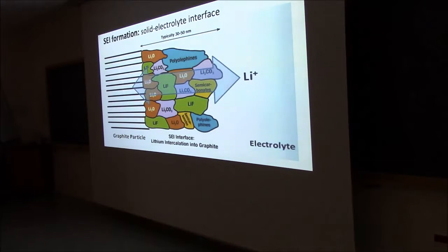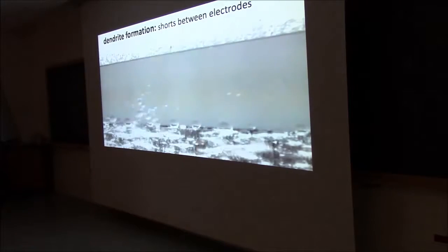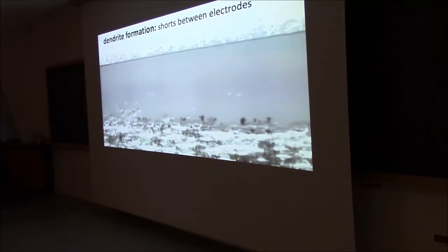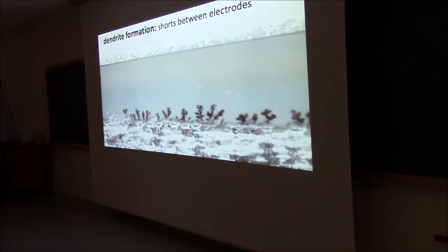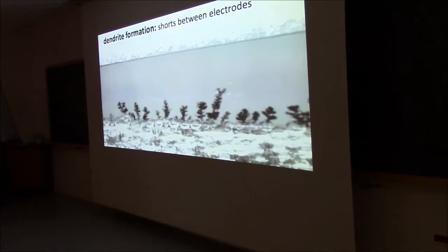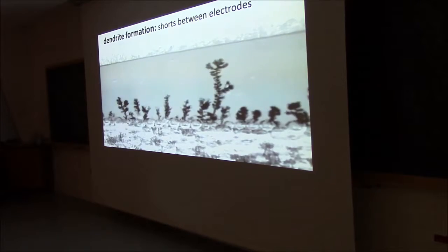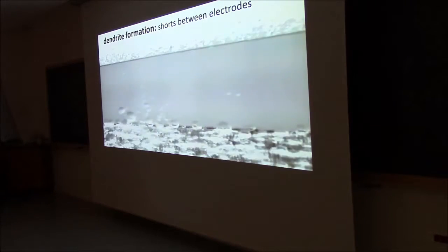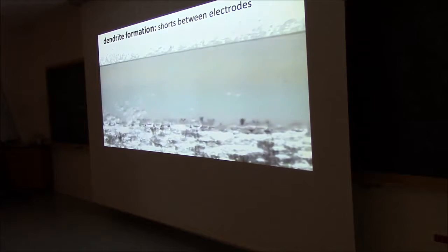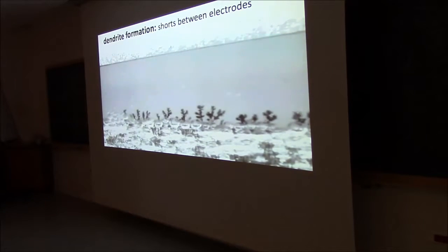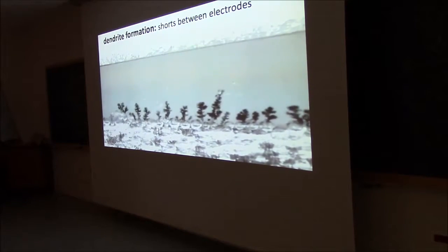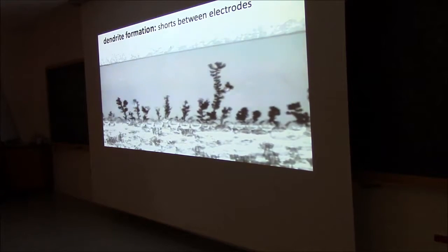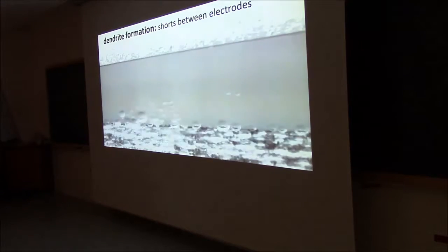Now why is this important on the anode? If your anode is not graphite, but purely lithium metal, and the lithium has to go in and out, it's not always happening like that. If lithium through this liquid has to go from top to bottom, it doesn't go in, it sticks to the surface, and it forms these dendrites in each cycling. At some point, you have a short and an explosion. And that's what's happening in some of the batteries, where at the interfaces, let's say the reactions are not perfect, the lithium is not intercalating, but it's stacking on the surface onto these structures.